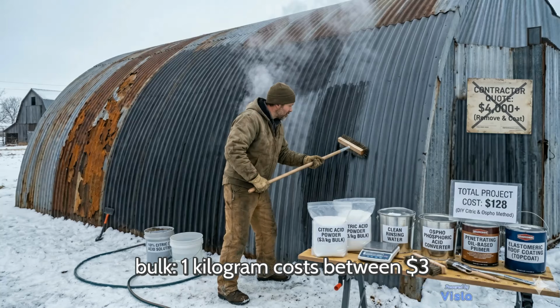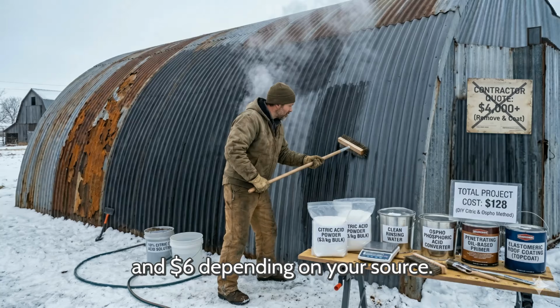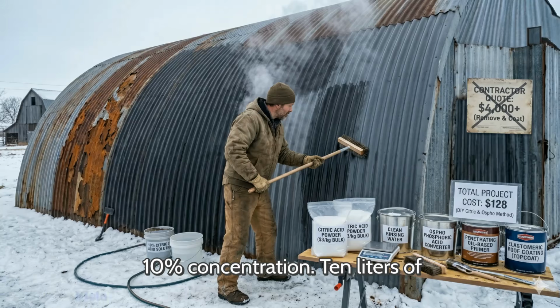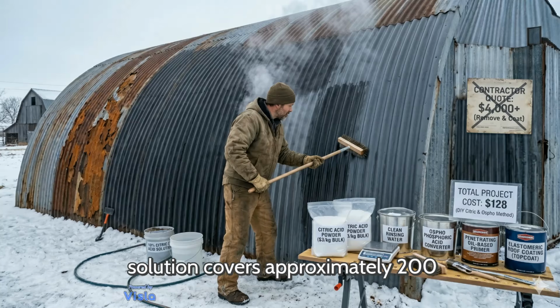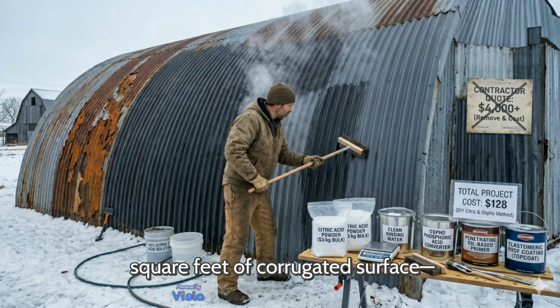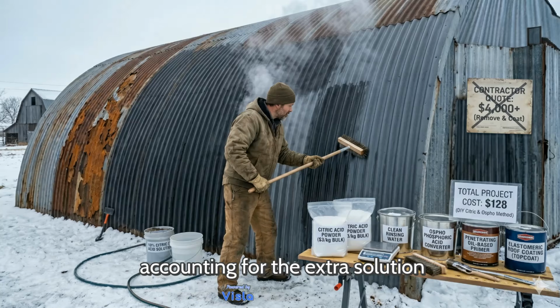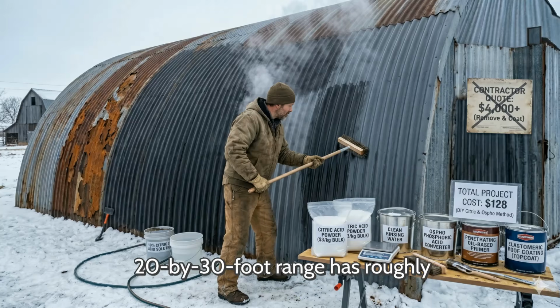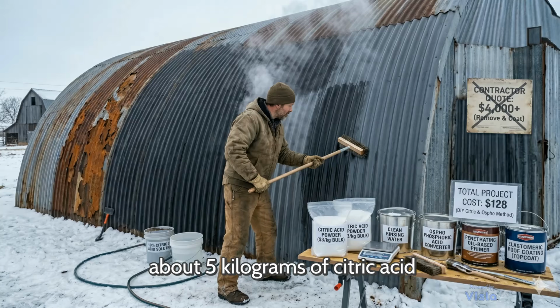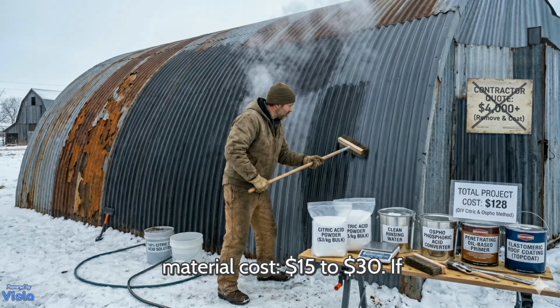Citric acid powder in bulk. 1 kilogram costs between $3 and $6 depending on your source. 1 kilogram of citric acid makes 10 liters of working solution at 10% concentration. 10 liters of solution covers approximately 200 square feet of corrugated surface, accounting for the extra solution that gets pushed into valleys. A standard Quonset hut in the 20 by 30 foot range has roughly 1,000 square feet of exterior surface. That means you need about 5 kilograms of citric acid for a complete treatment. Total material cost: $15 to $30.